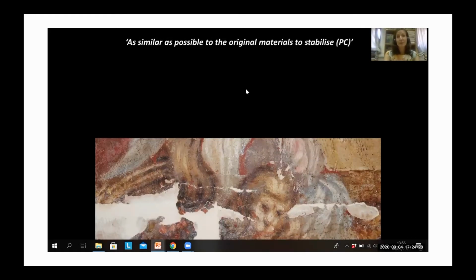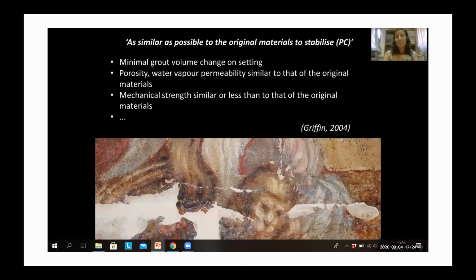So what do we say about injection grouts? That we would like them as similar as possible to the original materials to stabilize in terms of performance characteristics. So what does this mean? In general, meaning for any grout, we would like minimal grout volume change on setting. Why? Because we're trying to re-adhere two different layers at the interface, and it depends on the lamination, but often to fill a gap, to fill a pocket. So of course, if we inject something that then shrinks, we basically defeat the purpose. So the two different layers will not adhere anymore. So we always want minimal grout volume change in setting.